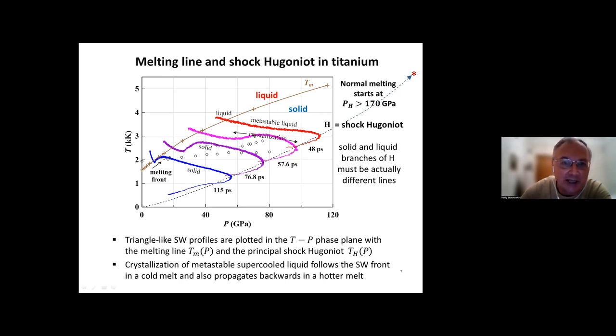With the decrease of pressure and temperature, these metastable liquids start to crystallize in two opposite directions, backward and forward. And after about 100 picoseconds, all of this liquid becomes solidified. And of course, the blue profile corresponds to the equilibrium solid state on this diagram. I have to say, in addition, that the normal melting is not shown on this plot. I just extrapolate to this right top corner, where the intersection of the melting line and the shock Hugoniot indicates the position of the onset of normal melting. But we are mostly concentrated on the cold melting here, which is why I showed it.